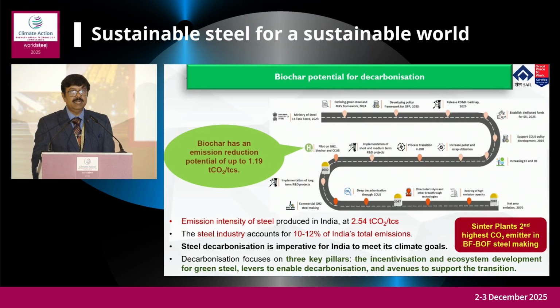In India, we are now operating with a carbon dioxide equivalent emission in the range of 2.4 to 2.5 tons per ton of crude steel. The sinter plant, as the second highest emitter of carbon dioxide equivalent, emits approximately 0.46 ton of carbon dioxide per ton of crude steel produced.